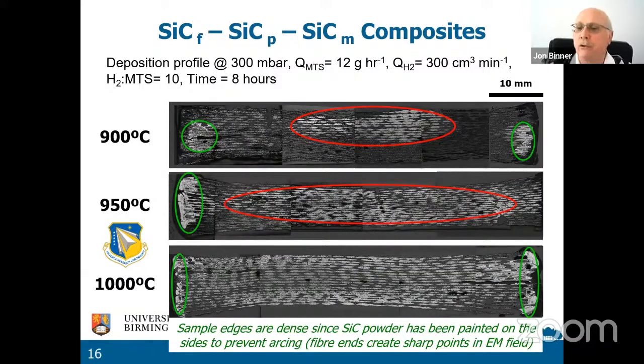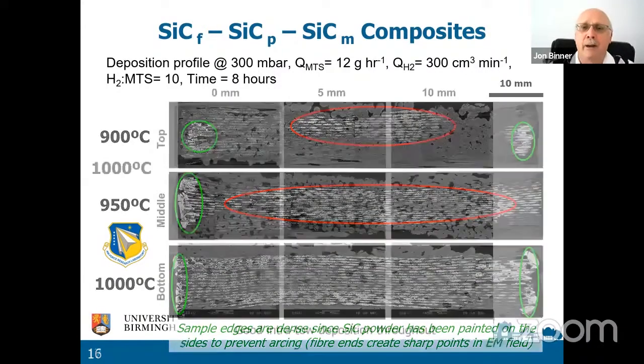Ignore the ends with the green circles. This is because we painted the ends of the samples with a silicon carbide slurry, and that was because we were getting electrical discharges where an individual silicon carbide fiber poked out of the edge of the sample. We built up the electric field in the microwave, and then just like lightning strikes, we got discharges. And we found by painting the ends of the sample, we could avoid that. So ignore the bits in green, it's the bits in red. And again, what you can see here is that you do indeed develop the inverse temperature profile. So it's nice to see that the theory actually is matched by experimental practice.